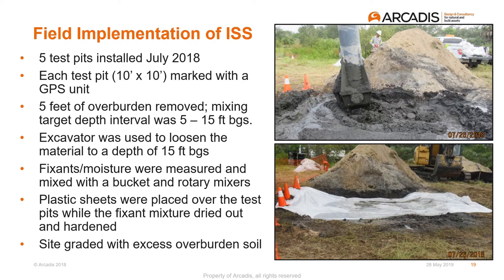We ripped off the top 5 feet to accommodate for the fluff of the fixant that we were adding. We did mix over the water table. Water was right around 8 feet, so we mixed about 5 to 15 feet below ground surface. There was enough moisture within the pit itself that we didn't need to add any extra moisture.